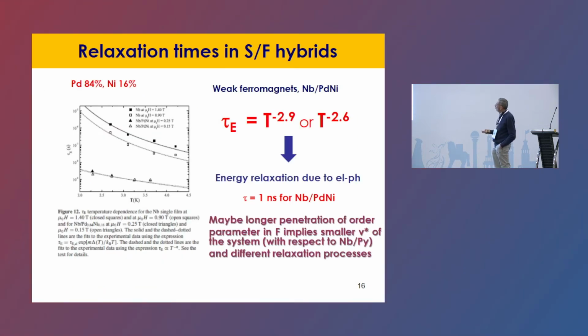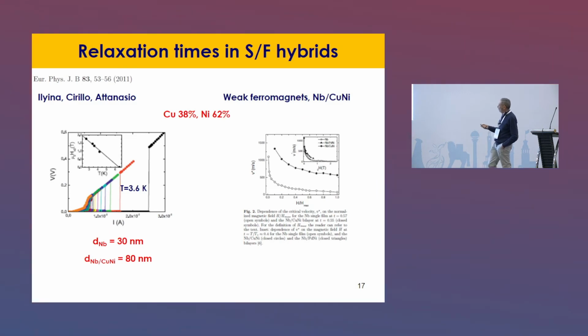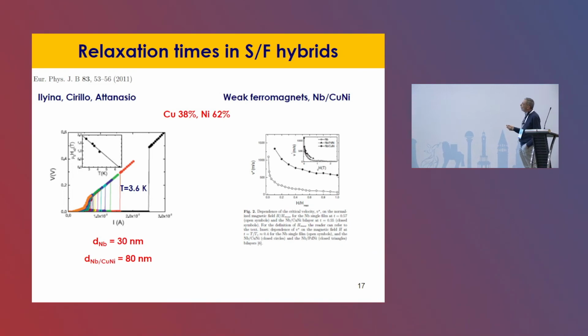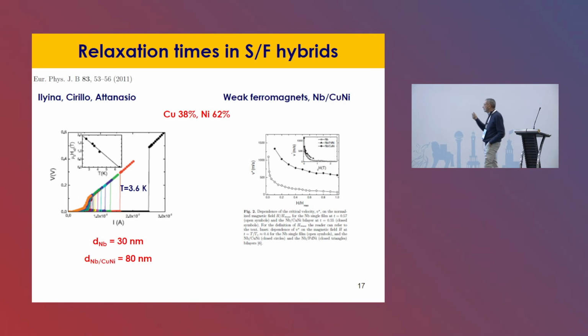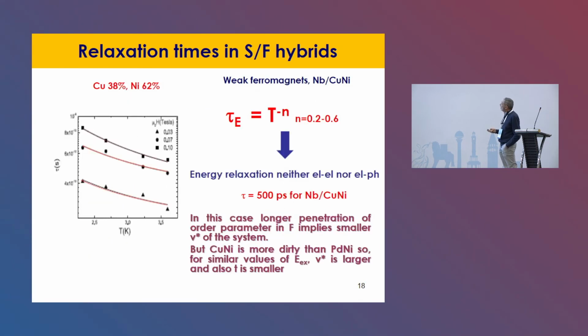Okay, well, this is the mechanism. Also the same with niobium copper nickel, and again this is niobium, and higher critical velocity for niobium copper nickel. In niobium copper nickel the critical velocity is even higher with respect to niobium palladium nickel, because they are both weak ferromagnets, but copper nickel is more disordered and its resistivity is higher, and this gives us a critical velocity which is higher in this case.